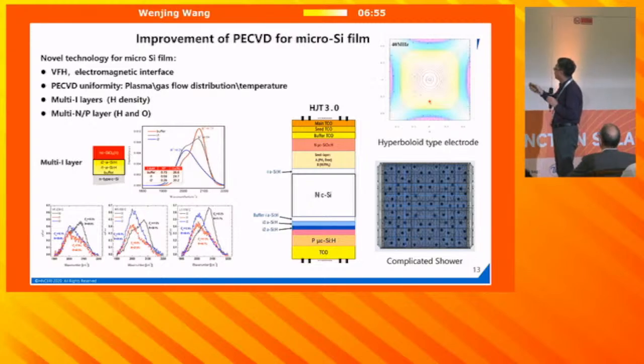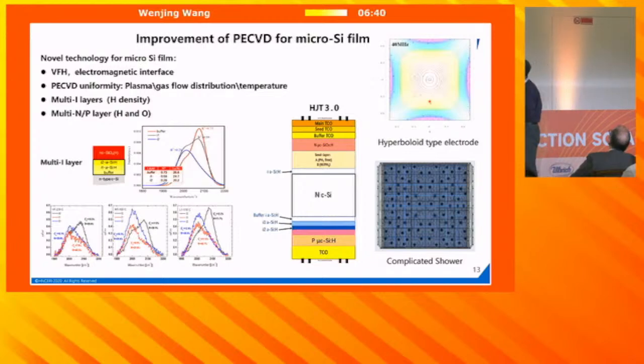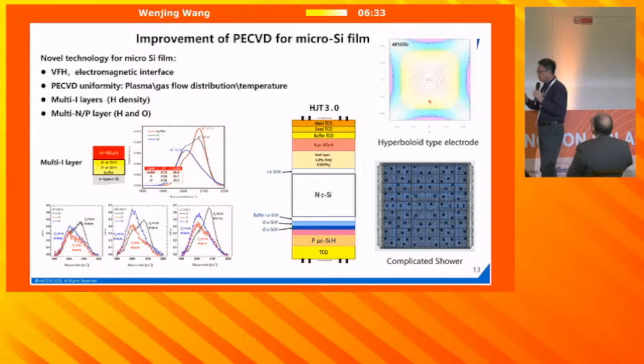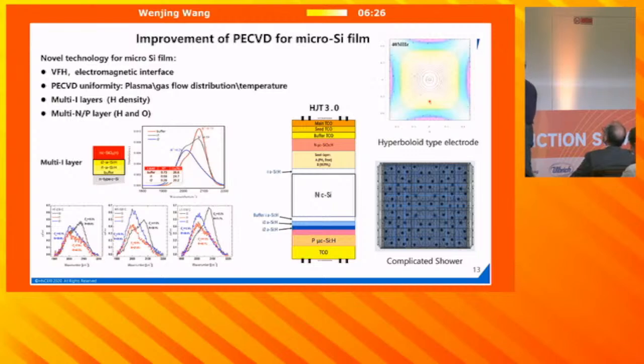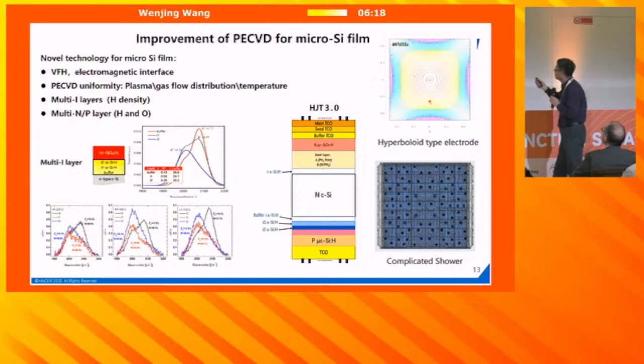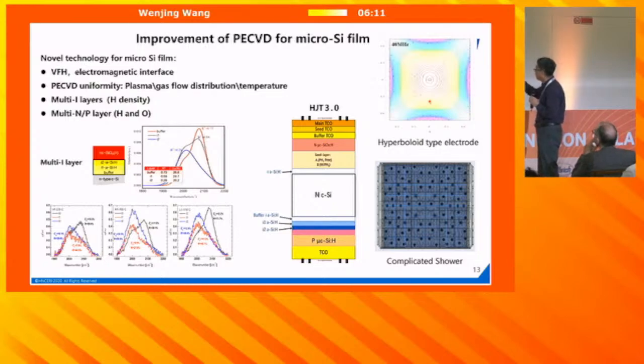And for the I layer, we separate it, only 2 or 3 nanometers thick. We separate a few layers, such as the I0 layer, I1 layer, and I2 layer. In the I0 layer, we put more hydrogen inside, so that will prevent epitaxy and also passivate the degradation of the surface. And for I1 or I2, you have to reduce the hydrogen to get a higher quality surface of the wafer.